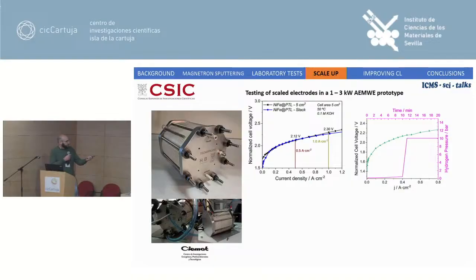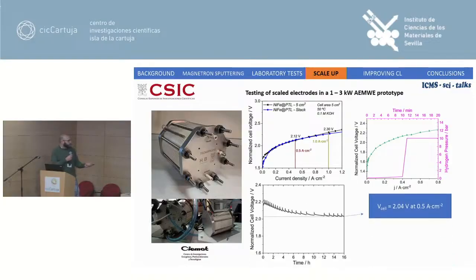We also were able to prove the pressurization of the cathode, which is a very important parameter in this kind of device when they work in industrial application. And also we kept our device working continuously for 16 hours at 0.5 ampere per square centimeter, with a production of 0.5 kilogram of hydrogen per day, and we could see how the voltage tends to decrease in the continuous operation mode.